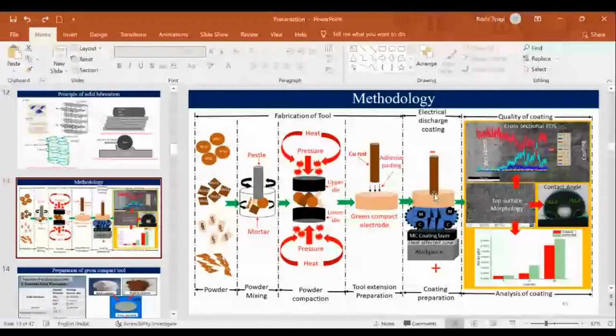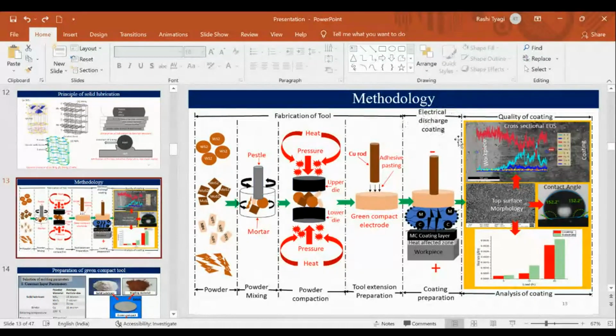So this tool is utilized to perform the electrical discharge coating operation of the workpiece and metal layer that I have told you. Then after performing the electrical discharge coating, we analyze the quality of the coating. How? By performing SEM analysis to check the morphology of the surface. Then we have also done the wear analysis to check the wear rate of the surface.